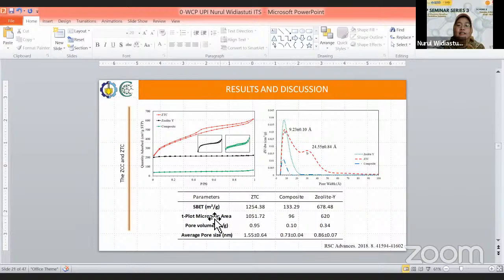And here is the result for the synthesis of the ZTC. We can see here that the surface area of the ZTC is much higher than the composite and the zeolite template in this case. And also the pore volume for the ZTC is 0.95 cc per gram, and the average pore size of the ZTC is much higher compared to the composite and the zeolite.